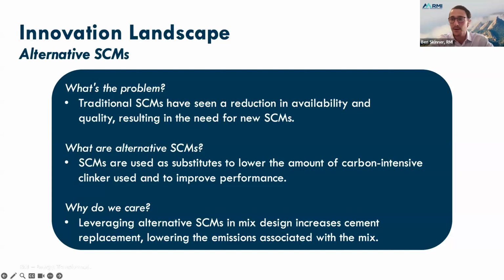And so SCMs are one great way to reduce the embodied carbon of cement blends. Of course, traditional SCMs are already used, type 1L cement being a more common blend that we're seeing these days, as well as use of slag and fly ash. But in the future, we expect a reduction in terms of availability, particularly on slag and fly ash as other industries decarbonize, resulting in the need for new SCMs. In addition to that, we do expect a great uptick in demand for SCMs in general. And so there will need to be new materials that come and fill that.